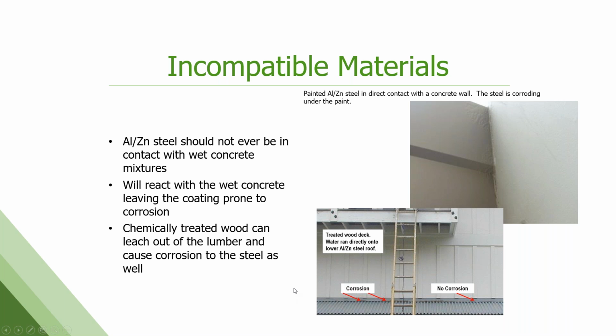Treated wood is an issue. Treated wood actually is usually treated with copper. Copper leaching out of that onto painted metal is a really bad combination, and that leads to premature corrosion.